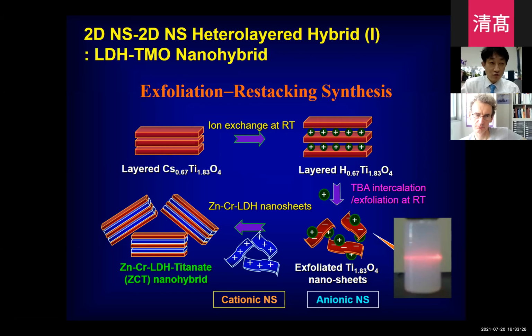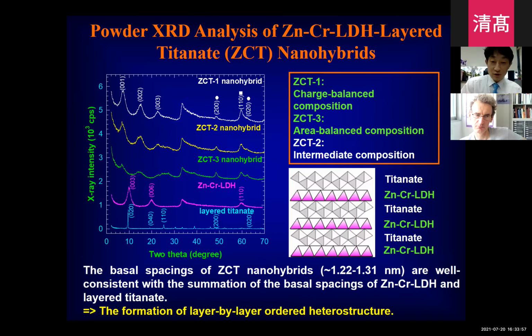So we synthesized many superlattice structures by using oppositely charged inorganic nanosheets. This is one example. We synthesized the titanium oxide nanosheet, which is negatively charged. As a counterpart, we synthesized cationic zinc chromium LDH nanosheet. In well-defined synthetic conditions, we can induce the layer by layer ordering of the two kinds of inorganic nanosheet. We confirm the formation of the artificial superlattice.